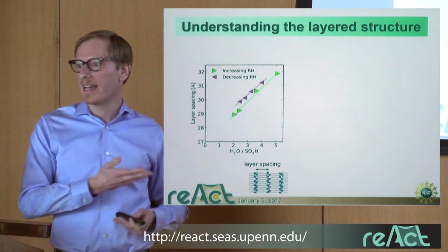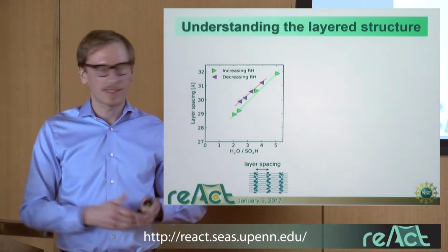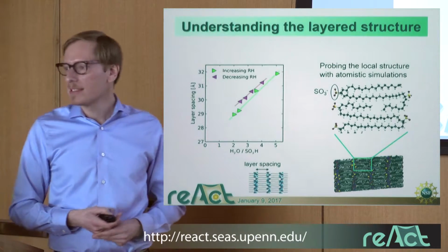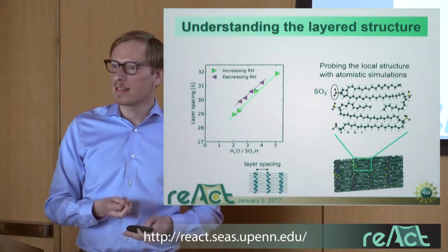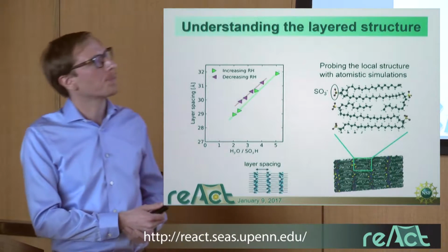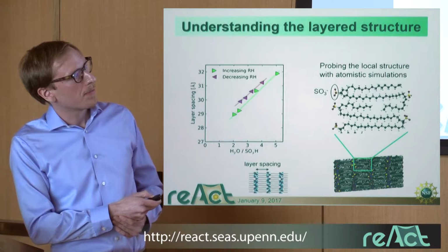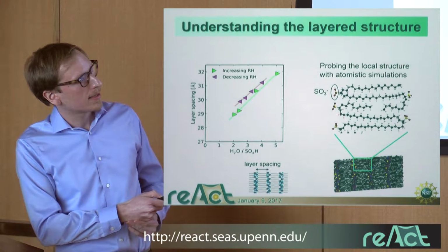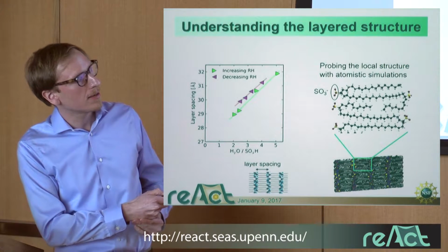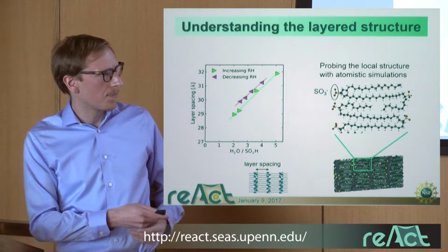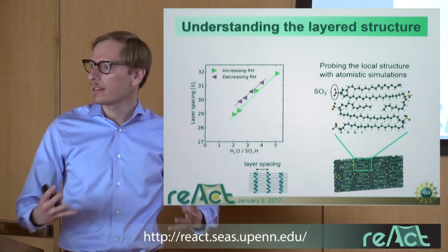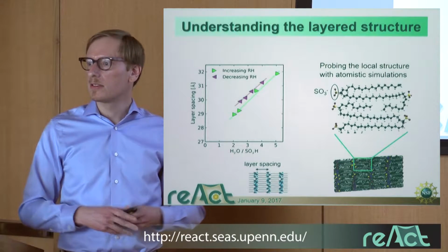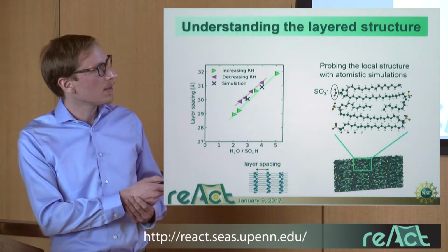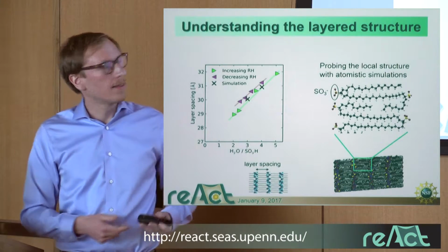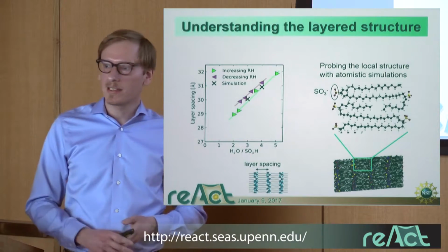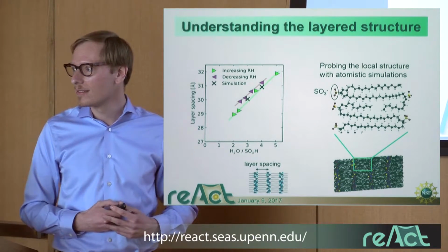Okay, so how well do we really understand this structure, the polymer conformations, etc.? I've done atomistic molecular dynamics simulations to really take a look at where the atoms are in this structure. And so here is the polymer, and you can see that the chains are folded and the sulfonic acid groups are here, located at the chain folds. And the results of these simulations, after relaxing the molecules into a low energy configuration, we obtain a layer spacing that really agrees well with experiment. So that's pretty cool, and that says that we really understand the structure well.